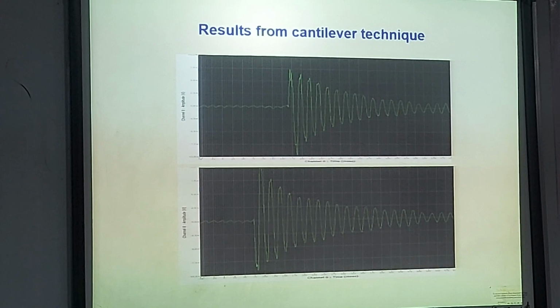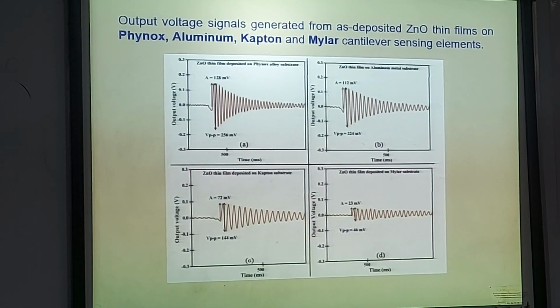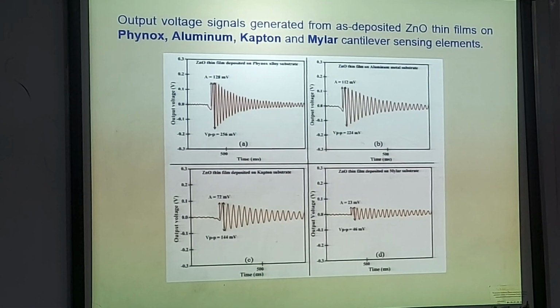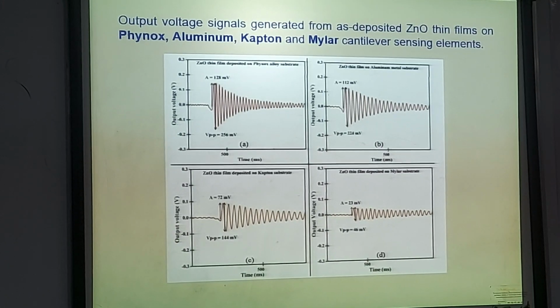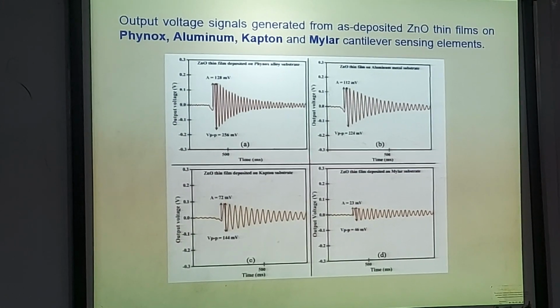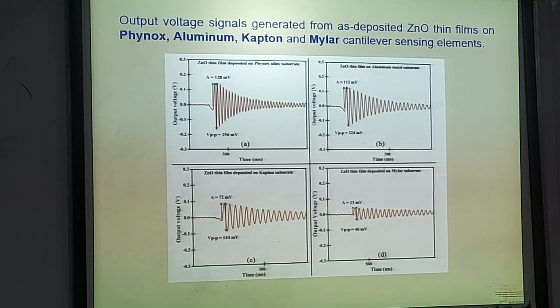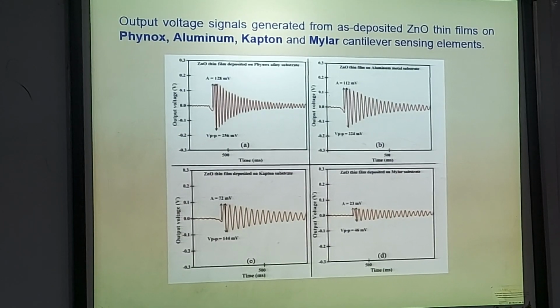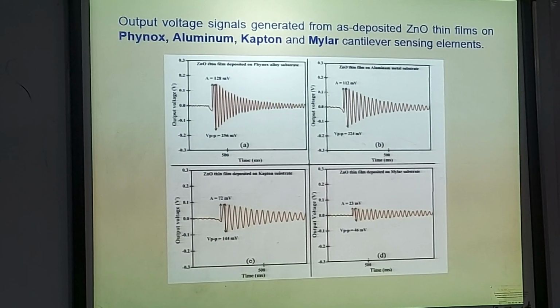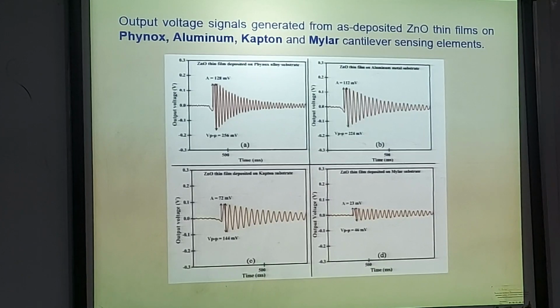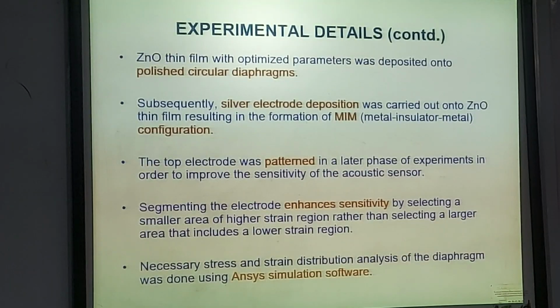After the confirmation of this, we tried different substrates. In addition to stainless steel, we tried Phynox, aluminum strip, Kapton, and mylar. We got a very good response with the Phynox, which is a very flexible material with good elastic property. These are some of the output signals that we could record.